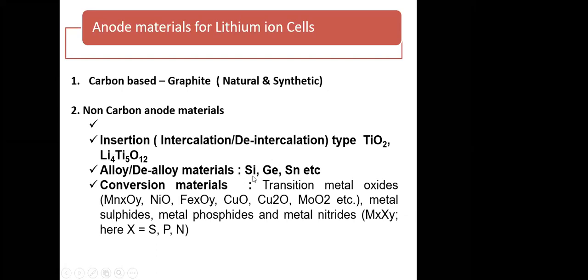only silicon is getting commercialized. All the high energy batteries which are coming are using 5 to 10% silicon. If you incorporate 5 to 10% silicon in the graphite, it gives more energy. Using pure silicon as an anode is a very tough challenge, because once you are making the cell, the cathode and anode have to be balanced by weight and by capacity. The capacity of silicon is very high, so coating the anode with respect to the cathode becomes very tough. That's why 5 to 10 or 20% silicon is what people have mostly achieved commercially, and at lab level it is going to increase to 50 to 60%.